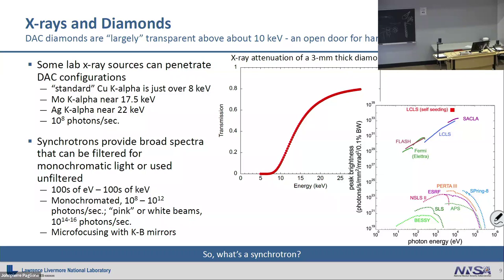So then the next thing that comes from the synchrotrons, especially these third generation ones, is how that interacts with the diamond. What's plotted here is the diamond X-ray attenuation. So this is the transmission of X-rays through the diamond as a function of energy for what I would say is a typical diamond anvil cell diamond. Typical DAC diamonds are something like a third of a carat on average, maybe 3 millimeters in width and height, something like that.